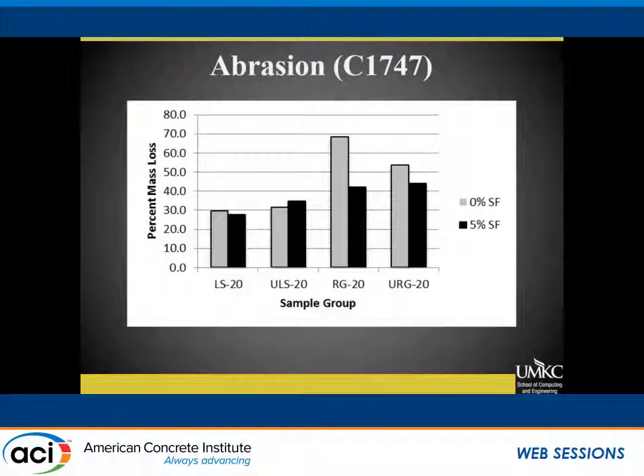The 1747 is a little bit of a different story. So 1747, you make 4-inch by 4-inch cylinders, 4 inches tall, at the right density or right void content. You take 3 of those, you throw them in an LA abrasion machine with no balls. You run it 500 revolutions, and then you measure mass loss. And so it gives you a relative idea for mixes, how durable they are.